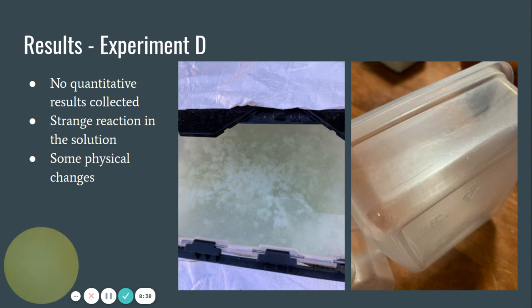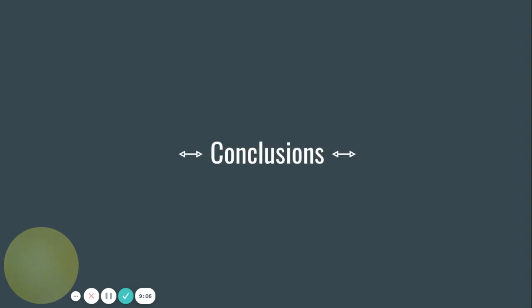However, there was some strange physical reactions. Around day 2, the bleach solution, as you can see in the image on the left here, became very cloudy, and it maintained that for the rest of the experiment. And as you can see in the right here, the walls of the polypropylene container became a little discolored and began to develop some ridges around the edge. So despite those two things, there was no weight change in either container.